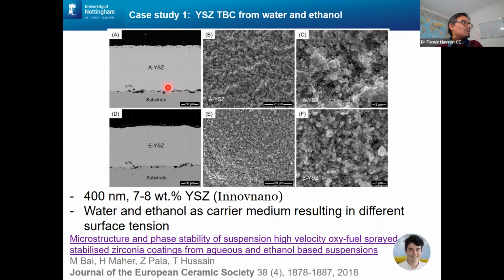So Harry was looking into AE, where A stands for aqueous and E stands for ethanol, the medium of suspension, which is YSZ, yttrium-stabilized zirconia. He was working with 400 nanometer, 7 to 8% YSZ, and the top surface of the coating, that's how it looks.